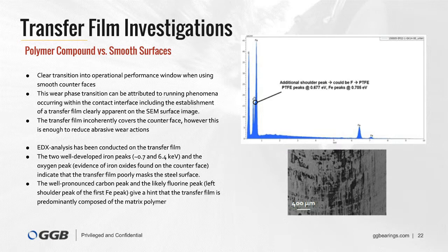We also investigated the chemistry behind the transfer film. For us, it's always important which part of the polymer transfers to the counterface. We did some EDX analysis to get information about that. What we see here is that we have two developed iron peaks and one big oxygen peak. This explains what we see in the SEM, that the transfer film poorly masks the steel counterface.